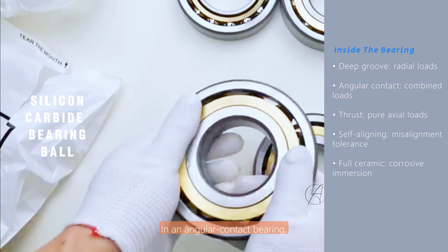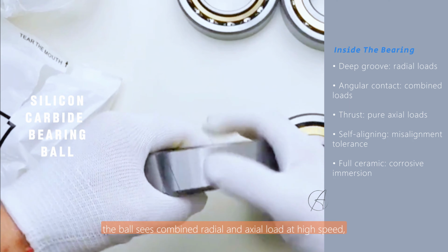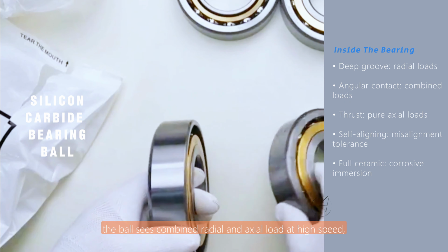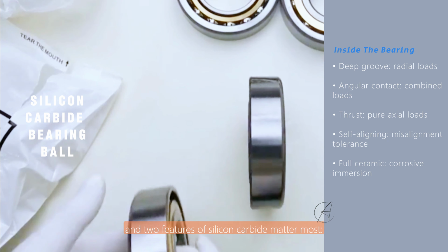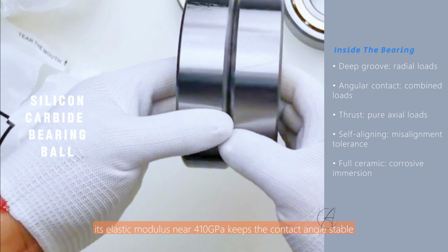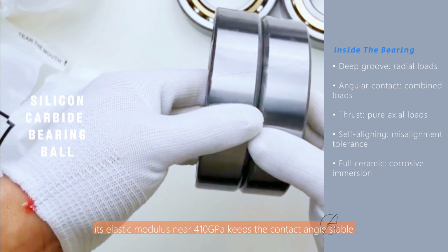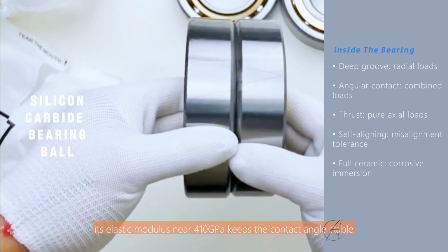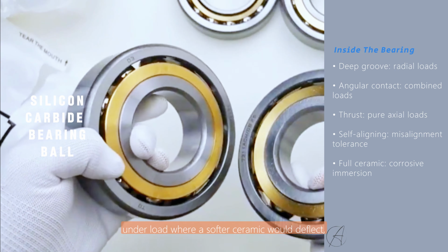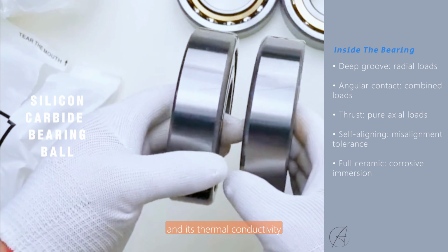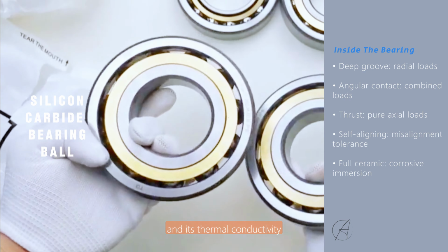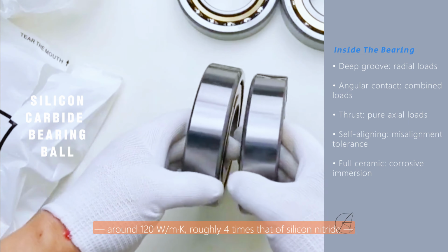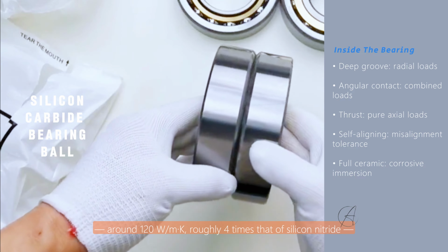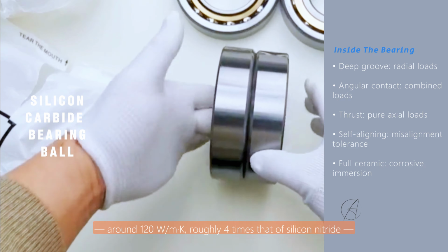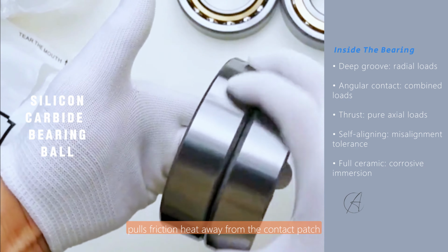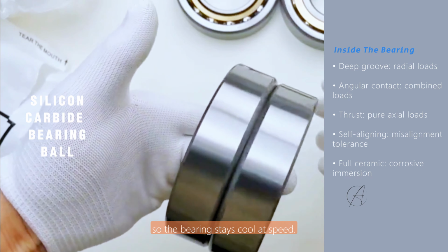In an angular contact bearing, the ball sees combined radial and axial load at high speed, and two features of silicon carbide matter most. Its elastic modulus near 410 gigapascals keeps the contact angle stable under load where a softer ceramic would deflect, and its thermal conductivity, around 120 watts per meter Kelvin, roughly 4 times that of silicon nitride, pulls friction heat away from the contact patch so the bearing stays cool at speed.